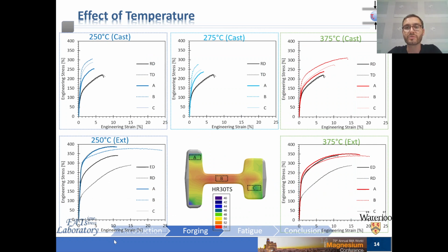Now, the second phenomenon which I'd like to discuss is the effect of forging temperature on the monotonic behavior, which is by far the most significant processing parameter. You can observe here that in general, higher temperatures, so the plot to the right here, have enhanced ductility but lower strengths. Furthermore, the increase in material properties is obvious between the as received and the forged materials. So you can definitely see that here in each of the individual curves, the as received being the black lines and the forged materials being the colored lines.